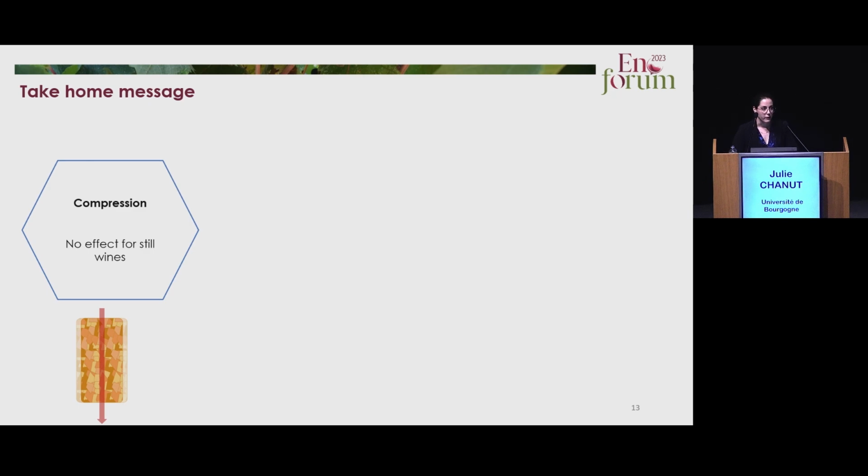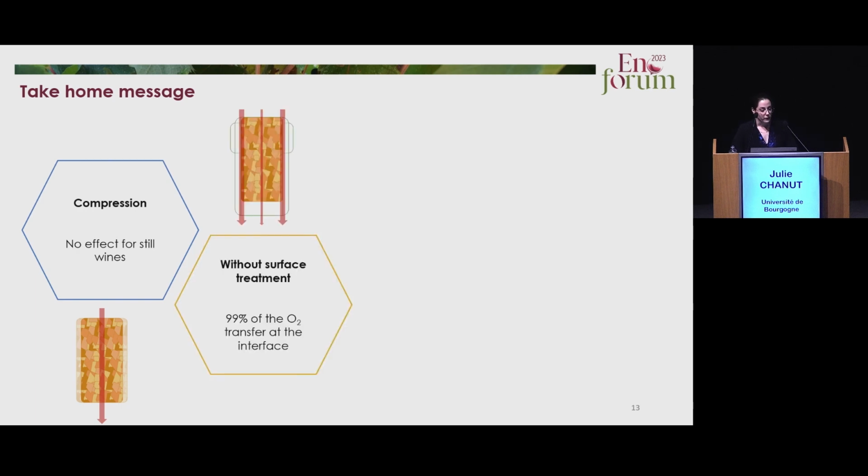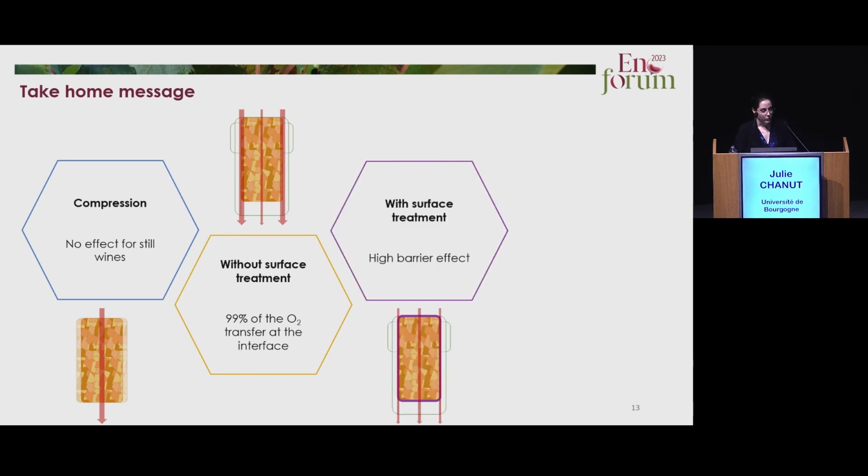OTR for corks only and still wines: there is a reduced effect of compression on oxygen transfer. Without surface treatment, the system is highly open to the transfer of oxygen, and 99% of the oxygen transfer occurs at the interface.